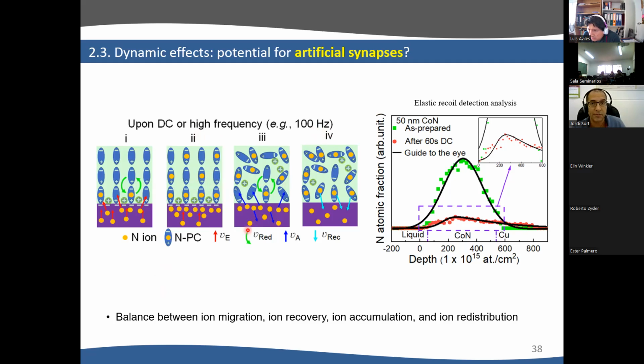When we stop the voltage, the electric double layer is destroyed, and then new chains arrive from the liquid and take the nitrogen that was accumulated at the interface, and then the nitrogen further goes to the liquid, and this would allow for the magnetization to be further increased.